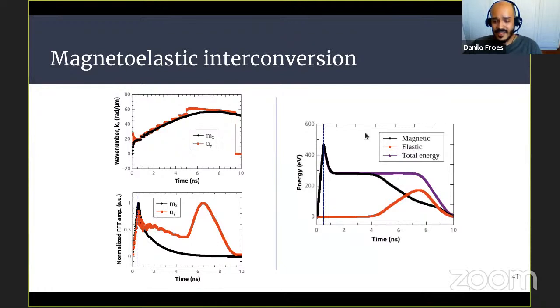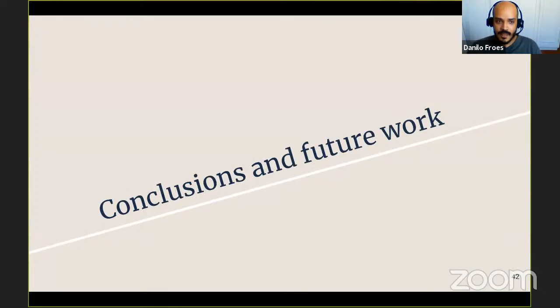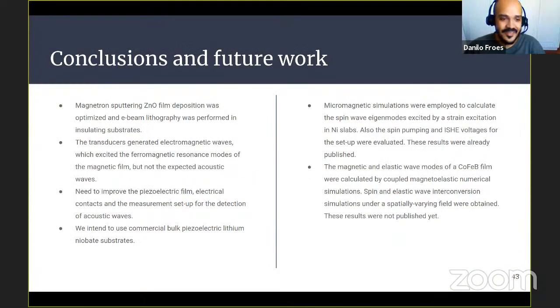Finally, I repeated the same experiment, but without any damping, neither magnetic nor elastic. And here's what we get. The total energy has a peak when I'm exciting, and then the left-going one is absorbed. Then the total energy remains constant, but there's a change between magnetic and elastic energy. This also shows that there is a conversion between magnetic and elastic modes due to the spatially varying magnetic field.